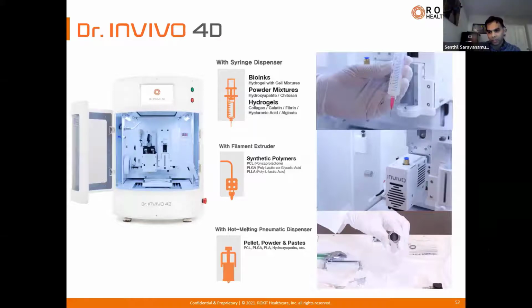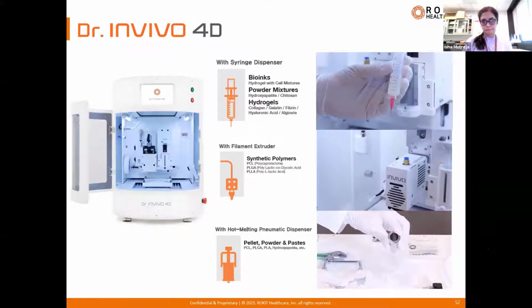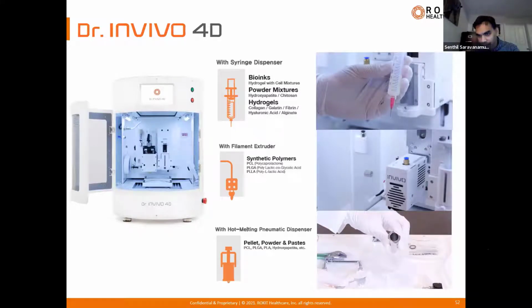Yes, ours is an extrusion printer as well. Now, the syringe dispenser is only for the soft hydrogel materials. The filament extruder, the input material has to be in the form of a filament. So that's more like your FDM. The hot melt is where you can put pellets, powders, paste, and one standout feature for our hot melt is that we have the highest temperature and pressure ranges available in a comparable competitor equipment.